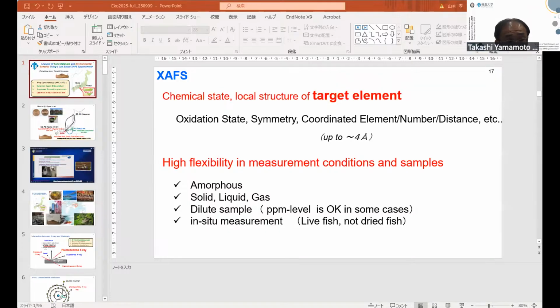This merit gives high flexibility in the measurement conditions and samples. The X-ray diffraction pattern cannot give information about amorphous materials, but XAFS is okay because it gives information about around 2 or 3 angstrom, the first or second coordination spheres. Amorphous is okay. Liquid and gas are okay. And dilute samples are okay, maybe down to ppm levels or ppb levels in some cases.